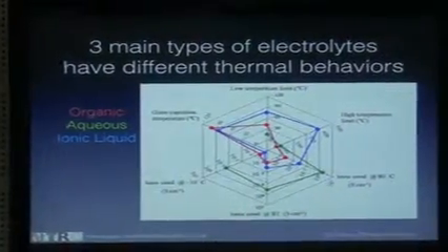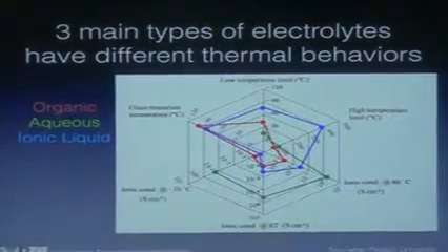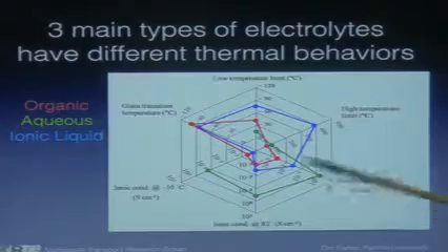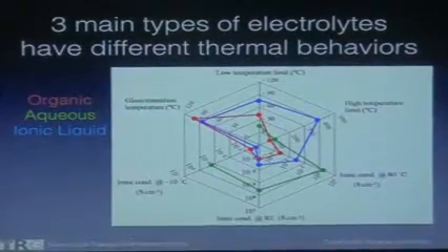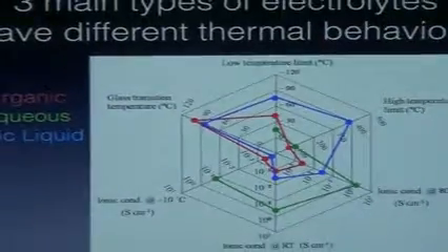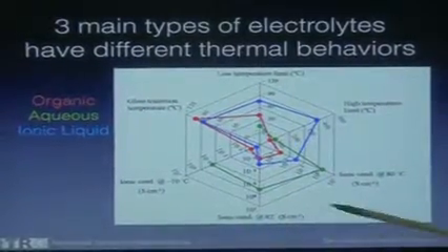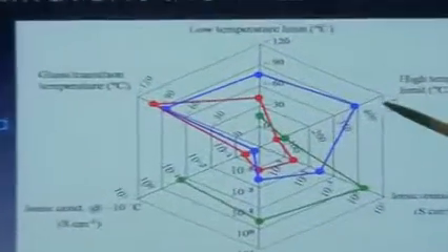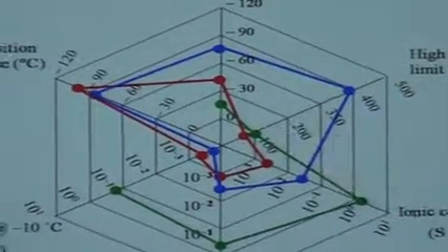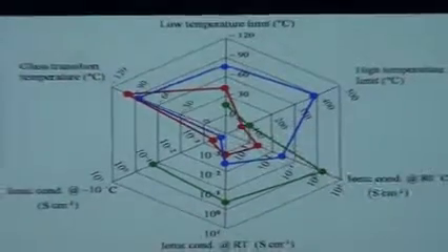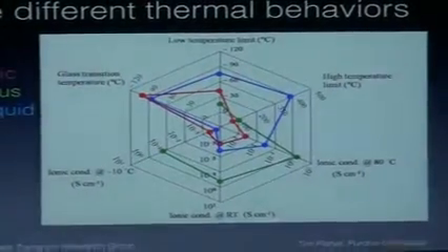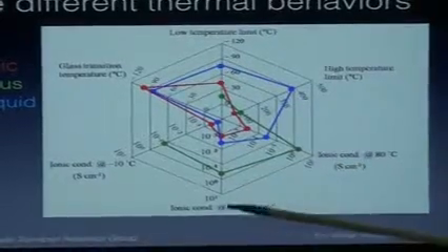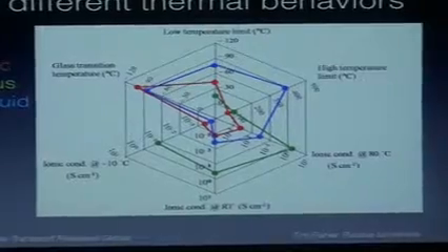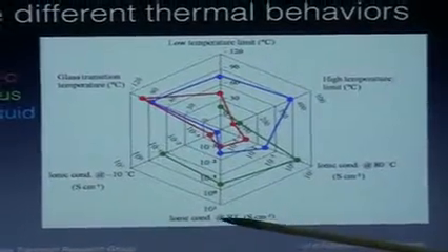And we've mentioned the 3 types of electrolytes. I've made a spider chart here showing their relative attributes for temperature effects or thermal behavior for organic, aqueous, and ionic liquid devices, or electrolytes. You'll notice that the ionic liquids look good. They have a wonderful low temperature limit. They have a great high temperature limit, a high glass transition temperature for essentially using them in low temperature environments. But they don't have very good conductivity. So their Achilles heel is a low conductivity, especially at low temperatures.